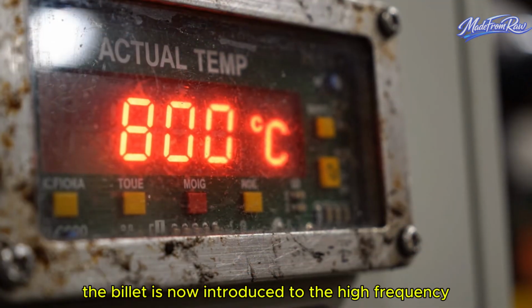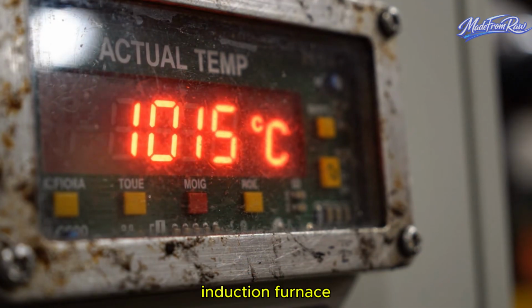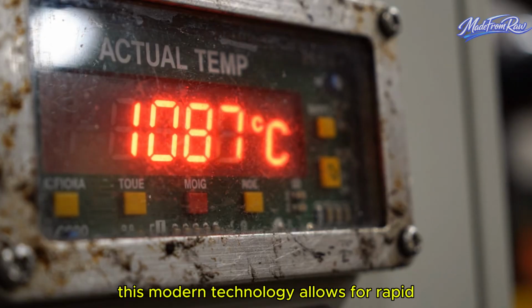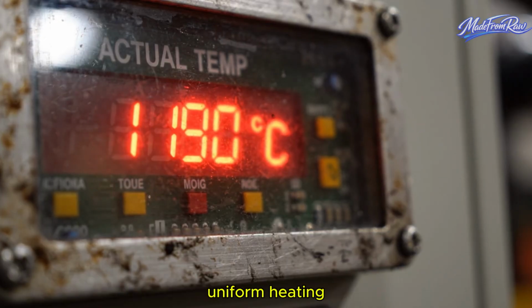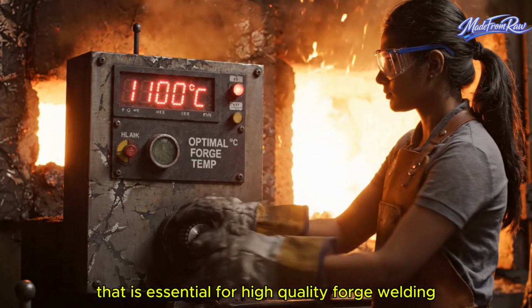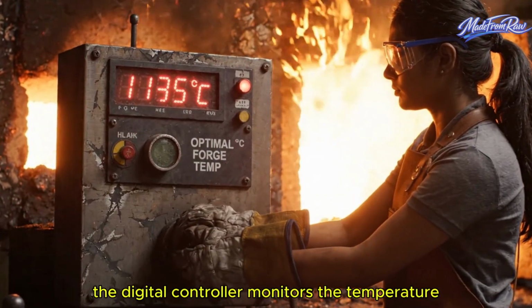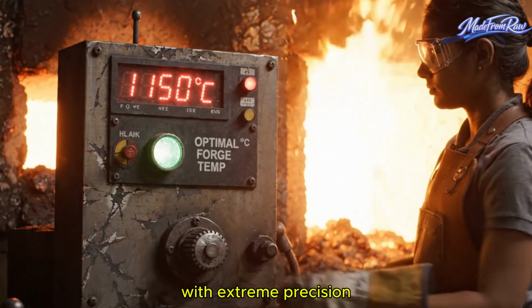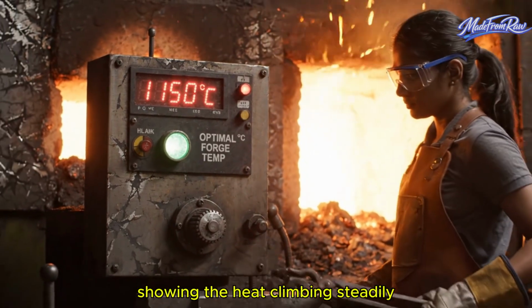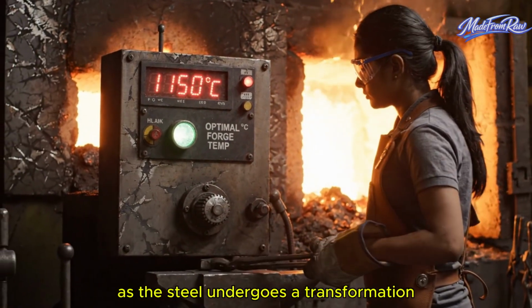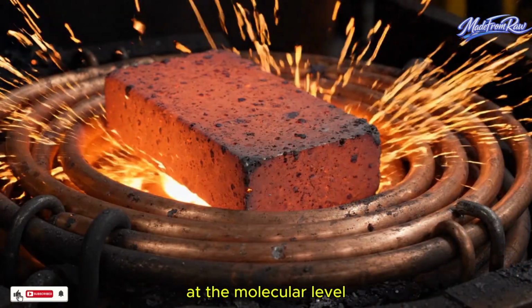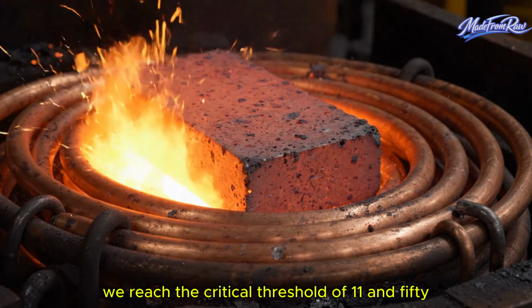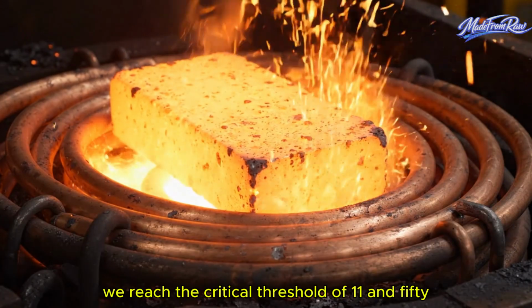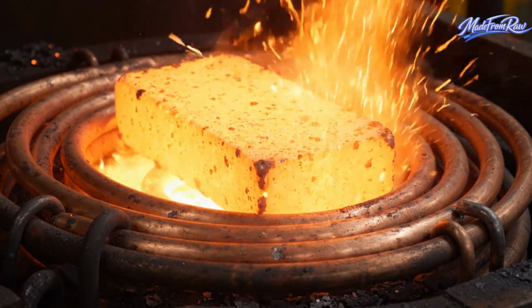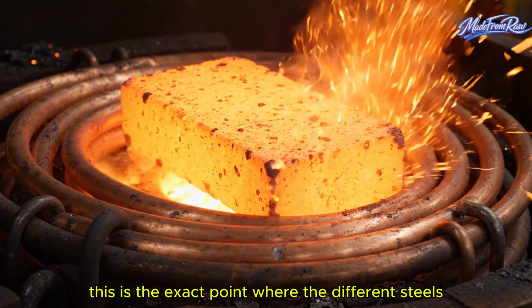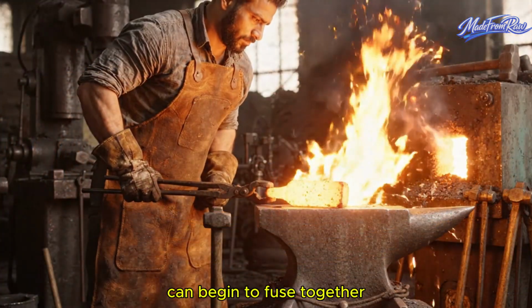The billet is now introduced to the high-frequency induction furnace. This modern technology allows for rapid, uniform heating that is essential for high-quality forge welding. The digital controller monitors the temperature with extreme precision, showing the heat climbing steadily as the steel undergoes a transformation at the molecular level. We reach the critical threshold of 1150 degrees Celsius. This is the exact point where the different steels can begin to fuse together.